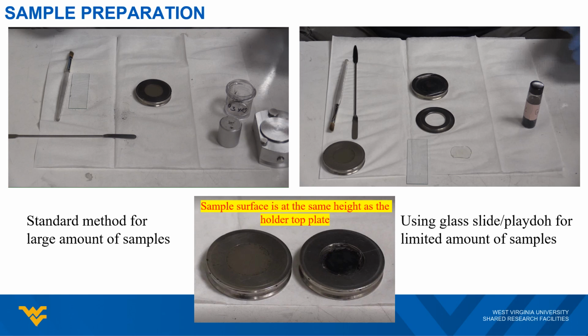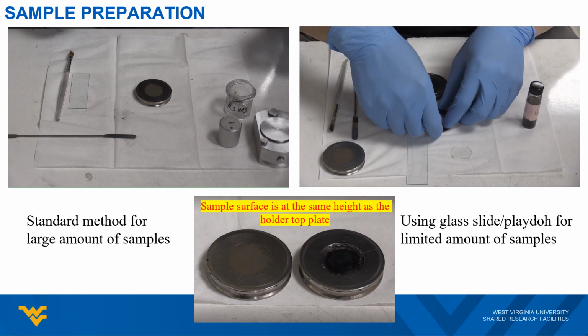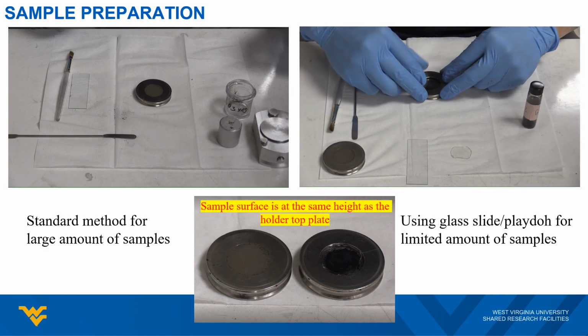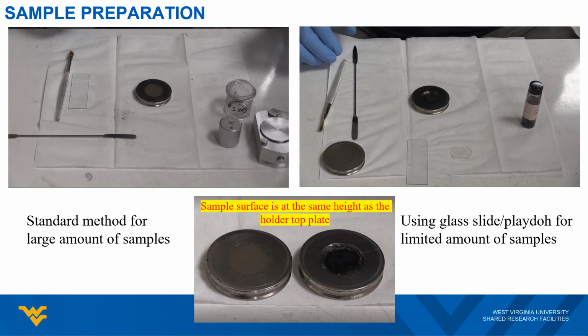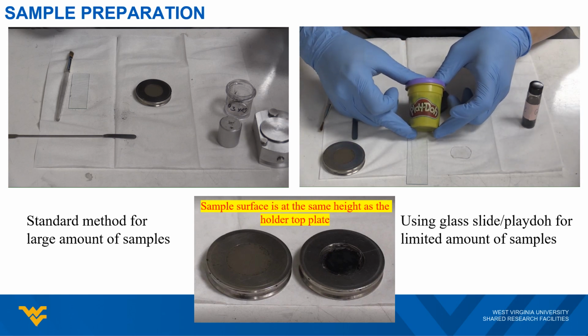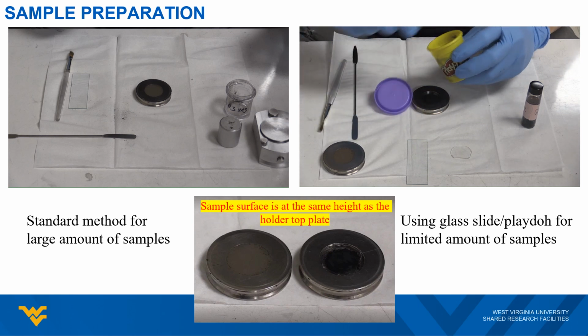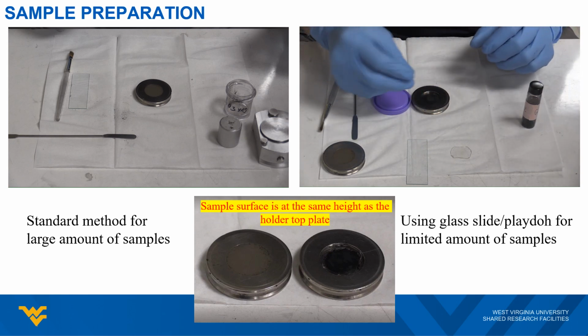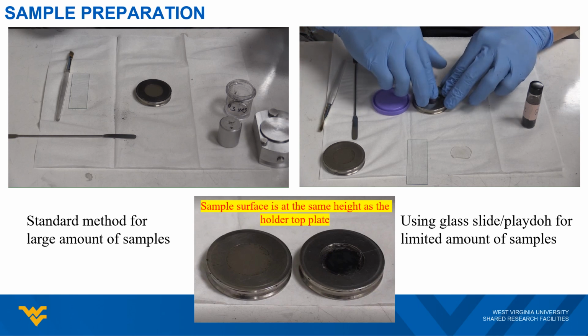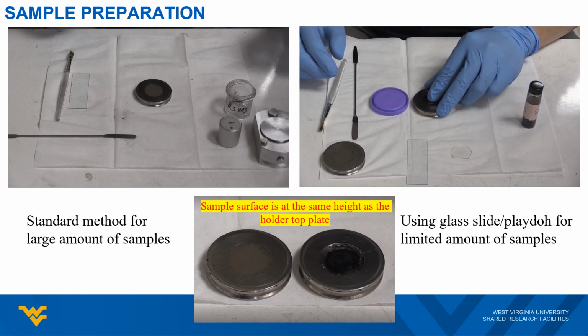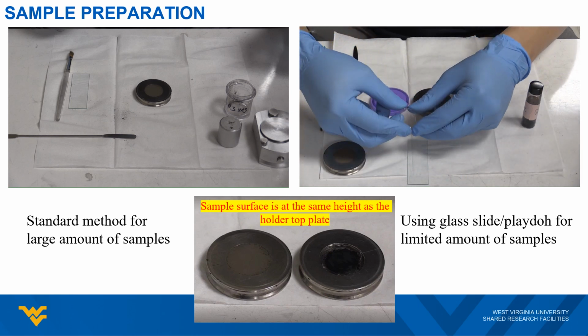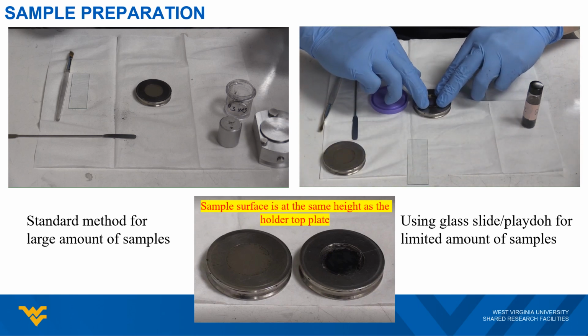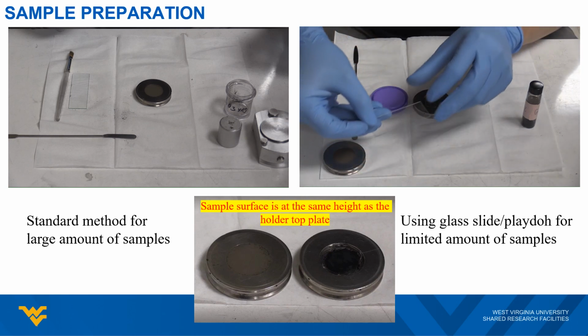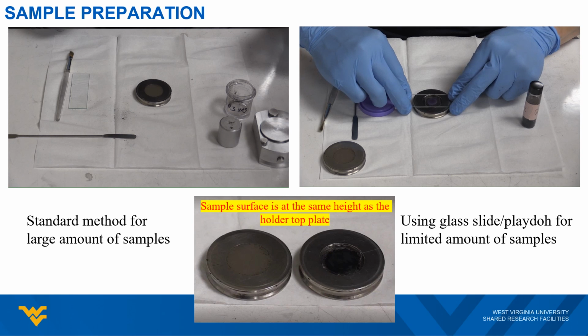If you have a small amount of sample, then you can use glass slides in your sample preparation procedure. The video on the right-hand side shows you how to prepare your sample using glass slides. Here we start with the whole sample holder, and then we apply a small piece of Play-Doh to the center of the opening space. And then add a piece of glass slide right on top. Make sure it will also fit into the opening space.